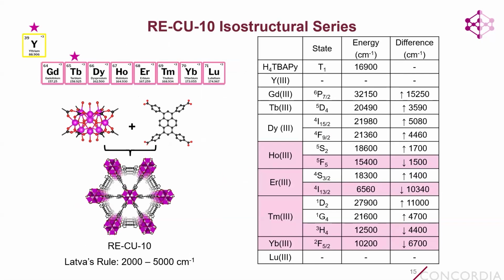And so the reason we thought that the identity of the rare earth element could play a role in the generation of singlet oxygen is twofold. One, because we have the heavy atom effect required to make the triplet state of the photosensitizer and generate singlet oxygen. So maybe that could play a small role. But also because these rare earth elements, these lanthanoids, have emitting states, these 4F energy levels, that can accept energy from the pyrene-based linker. So there's the potential for linker to metal energy transfer to occur in some of these analogs, specifically the ones from holmium to ytterbium. And so we wanted to see if this linker to metal energy transfer that can theoretically occur would be a competitive pathway with the generation of singlet oxygen and thus affect the photocatalytic results.